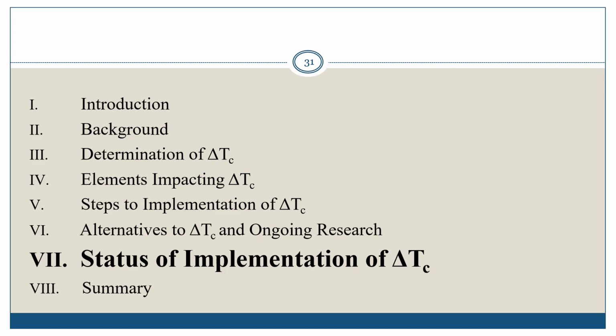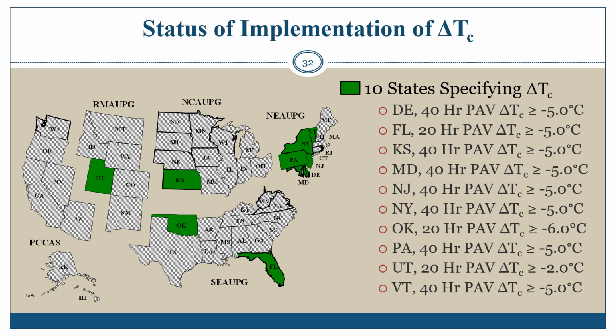Status of implementation of delta TC. A recent state-by-state review of the Asphalt Institute U.S. Binder Specification Database of published asphalt binder specifications revealed 10 state DOTs have adopted a delta TC specification parameter. This is slightly different to what the state DOTs reported by AI IS 240 to have adopted. Texas originally specified a delta TC of -6.0, but has since removed this requirement and is evaluating other methods and considering the relationship of S value to a given M value. Most but not all of these state DOTs adopted minimum limits of delta TC of -5.0. Oklahoma specifies delta TC of -6.0, and Utah requires delta TC of -2.0.